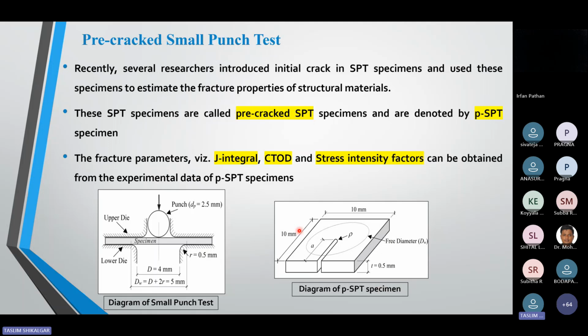And a similar methodology is used to test the specimens. And these are the dimensions. Here you can see the dimensions of the fixtures. And these types of specimens are known as the pre-cracked SPT specimens. This is also denoted in the literature as PSPT specimens. And with the help of these specimens, you can use any commercial software to get the J integral or CTOD or stress intensity factors at the crack tip.